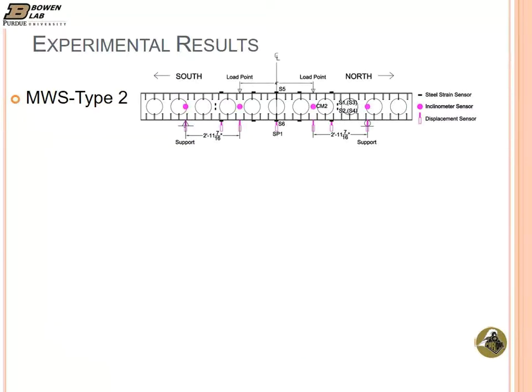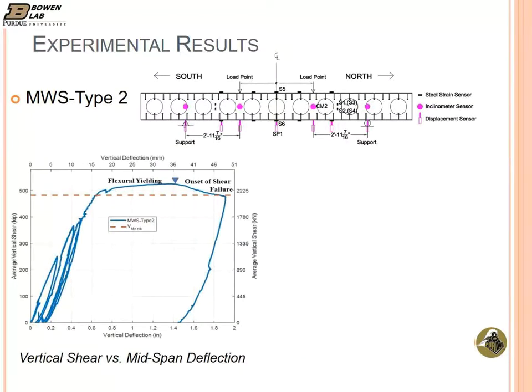Now let's talk about the type 2 specimen, which had the web plate in the longitudinal direction this time. We had a similar strain gauge sensor layout, so I'm just going to skip that one. But this was the experimental load displacement response. It's slightly different from what we saw for the first specimen, because again, it goes up linear. We had some nonlinearity due to cracking, but then we went into this flexural yielding zone because we started yielding the bottom face plate. We switched to displacement control from this point on, and as we were pushing it further with more displacement, the specimen just failed in shear.